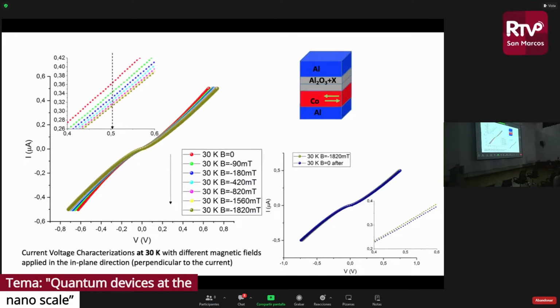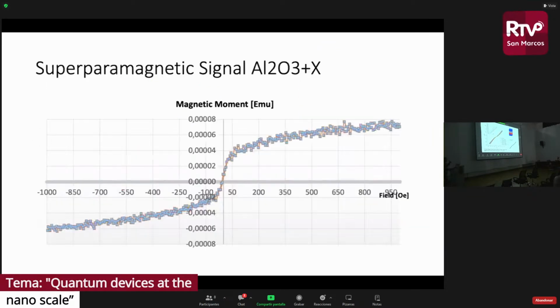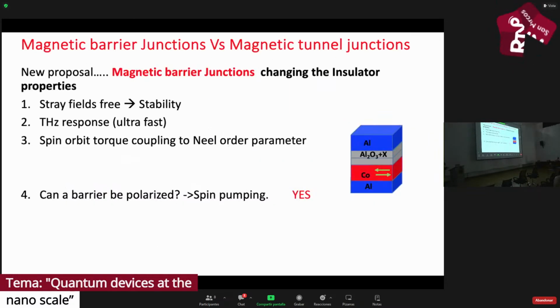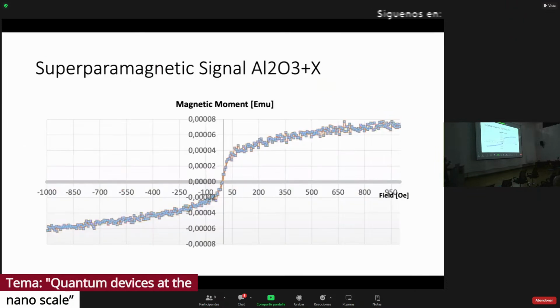When we put in the magnetic impurities, we get a magnetic response, but it's not just any response, it's a superparamagnetic signal of the magnetic properties. And it's important because it's a thin film solid state material. So we don't have nanoparticles. We have a solid film, and that's why it's important to have a superparamagnetic signal from that material.